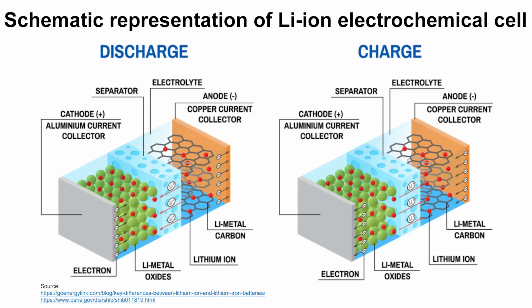A modern Li-ion battery consists of two types of electrodes, typically lithium cobalt oxide, LiCoO2, as the cathode material, positive electrode, and graphite, C6, as the anode material, negative electrode. To avoid short circuit, they are separated by a separator with a porous structure immersed in a non-aqueous liquid electrolyte using LiPF6 in a mixture of ethylene carbonate, EC, C3H4O3, and at least one linear carbonate, for example, diethyl carbonate, DEC, C5H10O3, dimethyl carbonate, DMC, C3H6O3, ethyl methyl carbonate, EMC, C4H8O3, with many other additives.